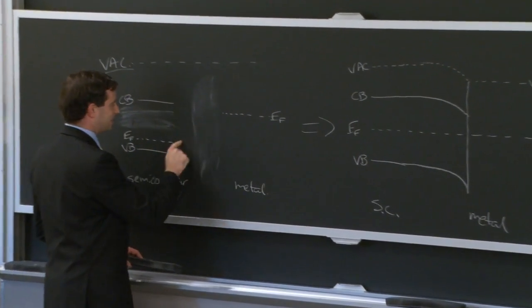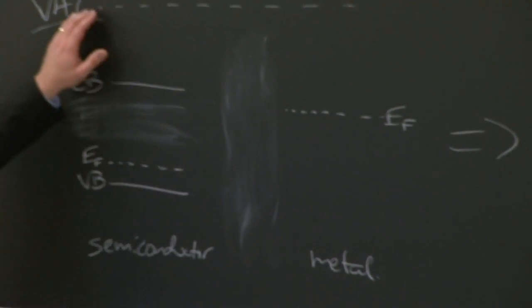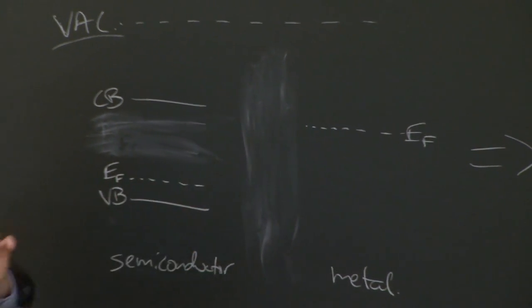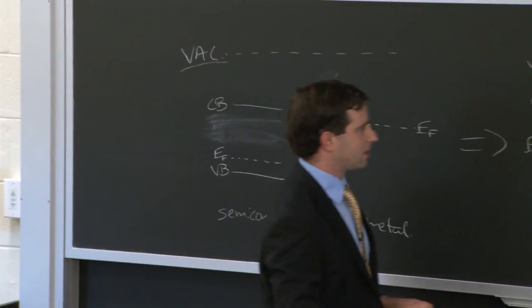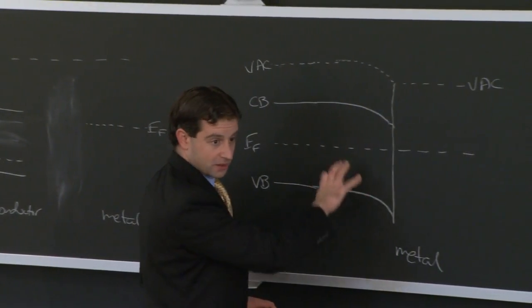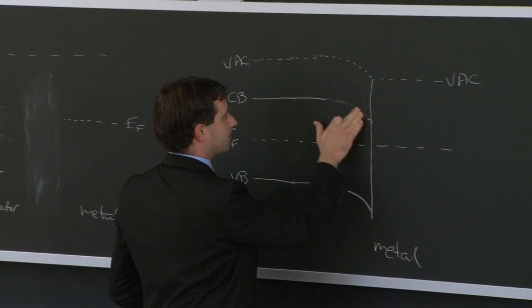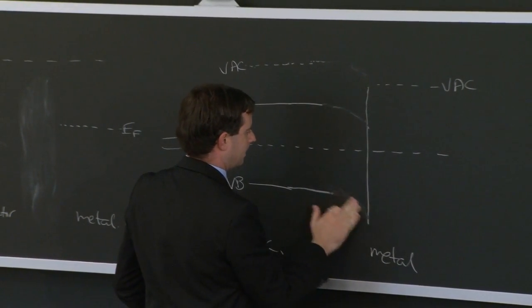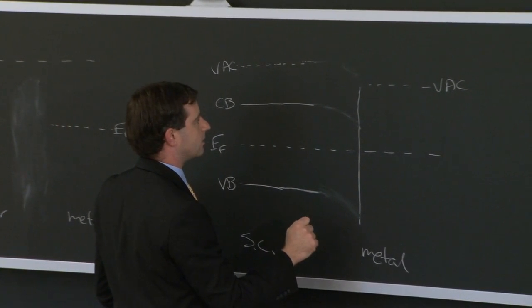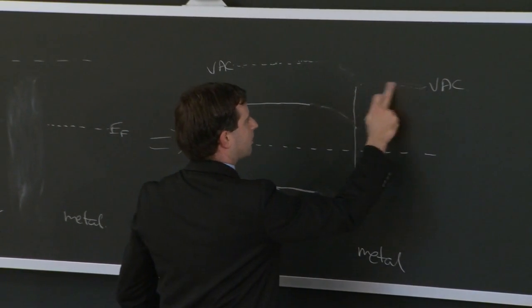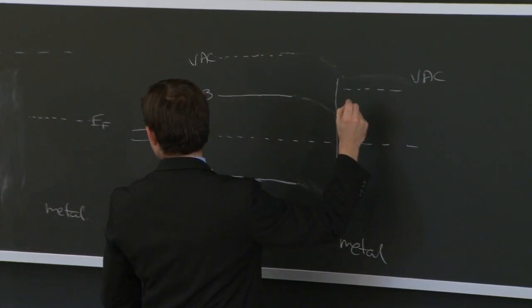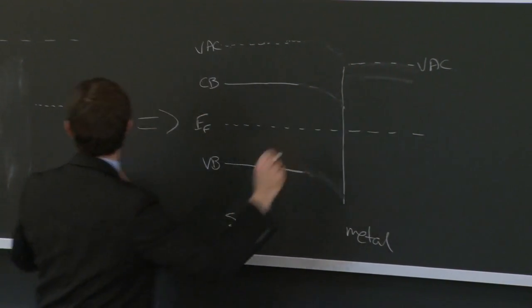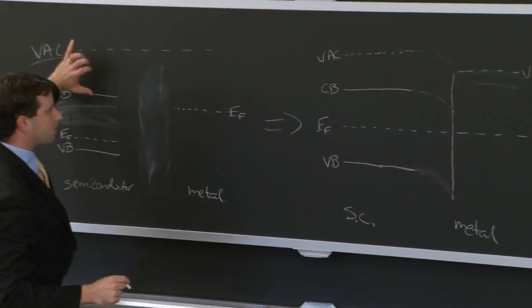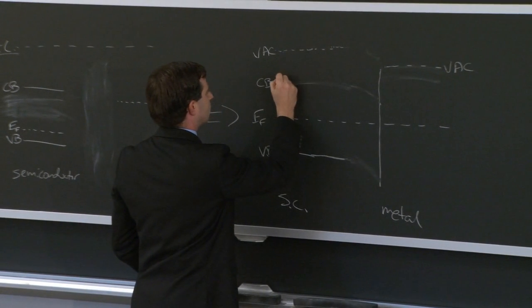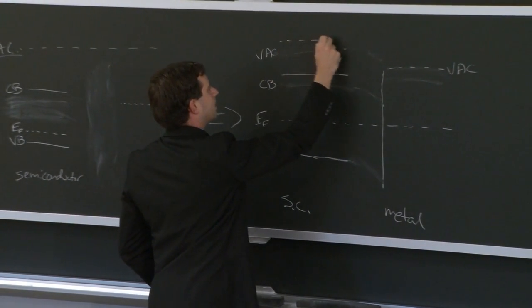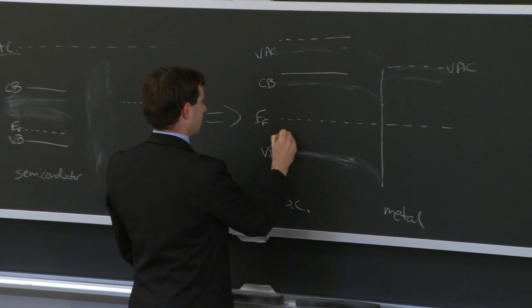The reason is I want a big delta in my Fermi energies right here if my vacuum level is constant, to exacerbate that band bending at the interface. And so now I'm going to get a pretty drastic band bending. It'll be even more extreme than what I drew here, but let's say it's fine. So what we would have to do is move this down further. Actually, no, sorry, this wouldn't change because this is still the same. What we've done here is essentially shifted everything up further. So to be more precise, we'd have to move this up, move this up, and move this up as well. Again, P-type material.